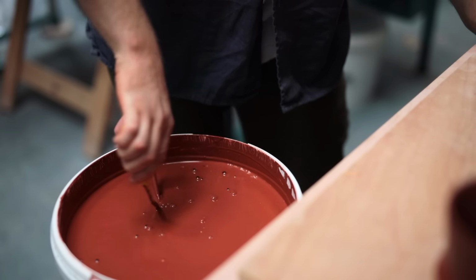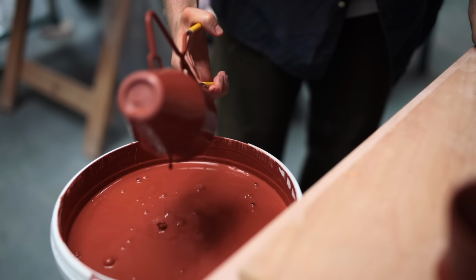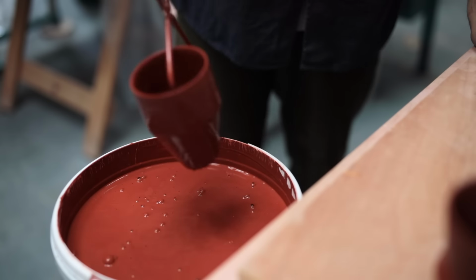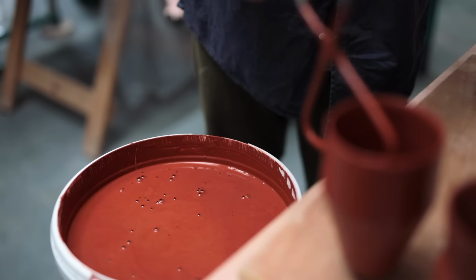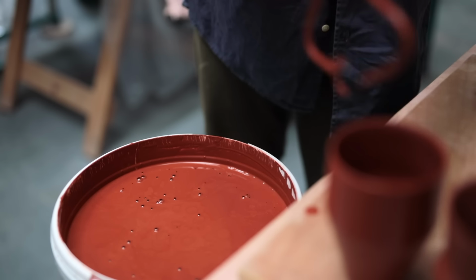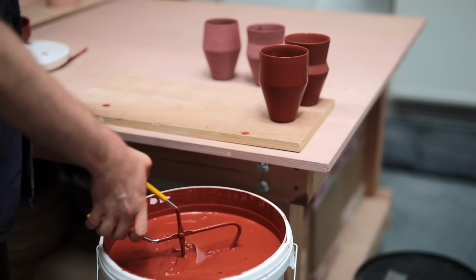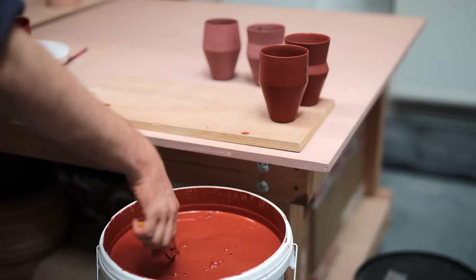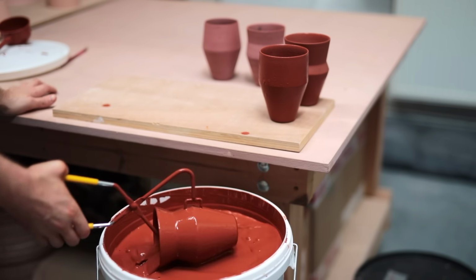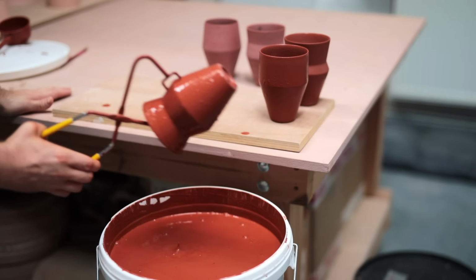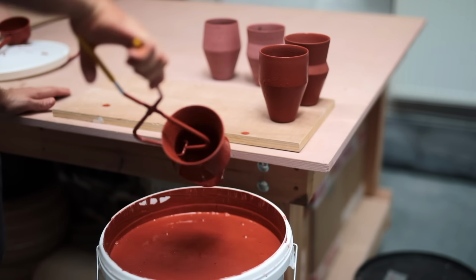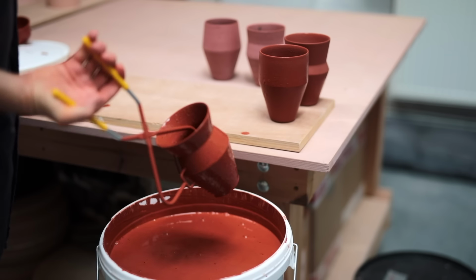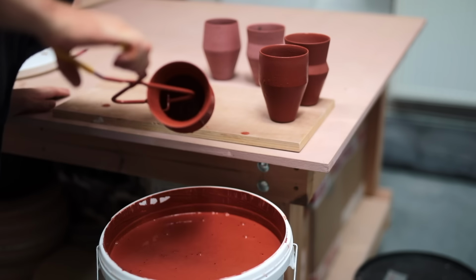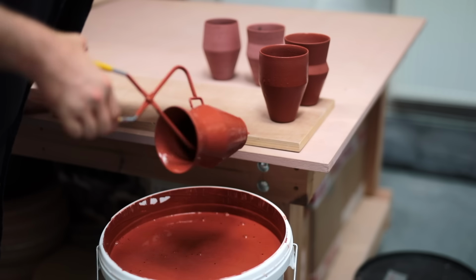You can see here how the thin glaze flows off the wax, which means I have to spend less time tidying it up later. There is a lot I'm thinking about when glazing, such as how long each pot is dipped. These pieces have relatively thin walls, so I can't dip them for too long, otherwise the clay becomes oversaturated with water, resulting in the glaze taking a really long time to dry. And if that happens, there's a chance the glaze can crack and peel off the pot.